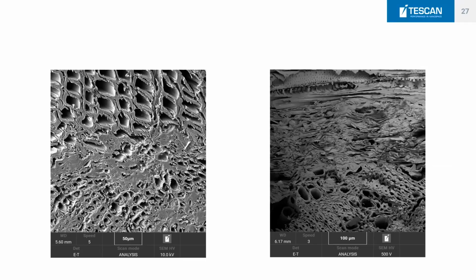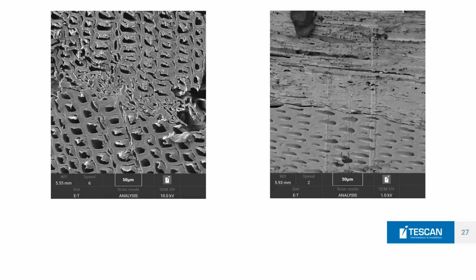Another point is that if you have wood-based composites, they are bonded somehow with adhesive. So you can start observing how the adhesive penetrated through the cell walls, or what the interface looked like. On the wood-based composites, you can clearly observe some of the parts where the particles are joined together, and you can identify the bond line. On the right-hand side, you can see the alternative particle board where the adhesive, for example, just glued together some softer parts of the material, and you barely found any bond lines.